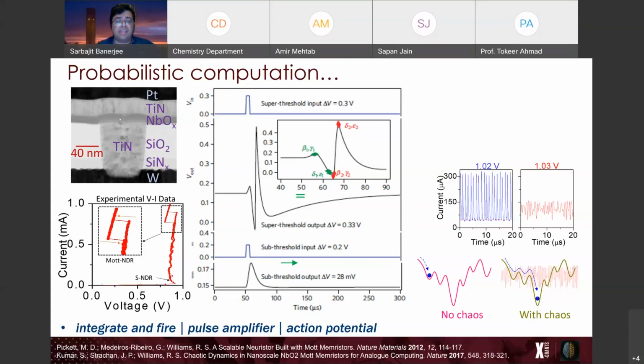This is what the structure looks like. It's very simple. It's a two-terminal device, where you've got titanium nitride, which is a metal, and platinum on two sides, and you've got niobium oxide in the middle. And you've got coupling of these metals. What you end up building are these oscillators. So you've got this sort of oscillator, and depending on the voltage applied and the resistance and the capacitance in the network, you end up getting a chaotic oscillator.